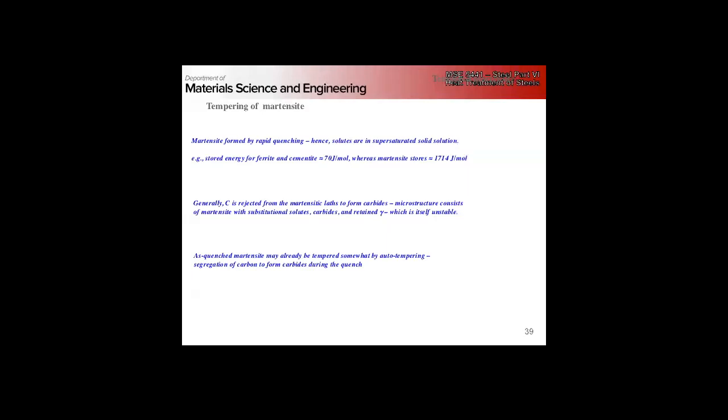So remember, we're at a lower temperature. Our substitutional solutes are going to partition very slowly. There's no crystallographic orientation change associated with the tempered martensite. We're not changing our grain orientation at all. We're dissolving out, moving out the carbon. We're going to BCC ferrite.